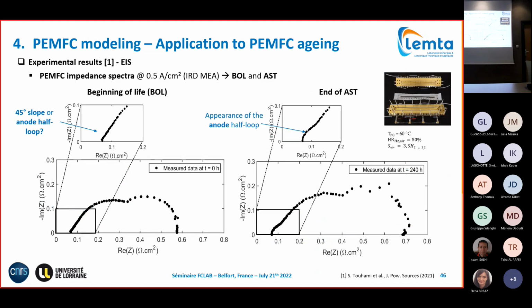Here the first question to answer is what is the adapted circuit we use for our EIS analysis. Here we show a spectrum measured at the beginning of life, characterized by two loops and something that could be a 45-degree slope, or a very small half loop, we don't know. It's the first thing we have to analyze. At the end of our AST, we saw the appearance of an anode loop, meaning our AST induced aging of the anode. So it was a surprising contribution.